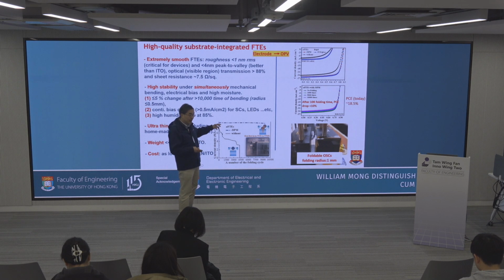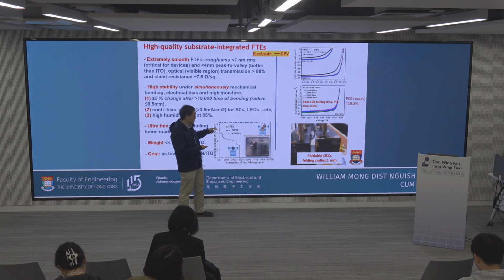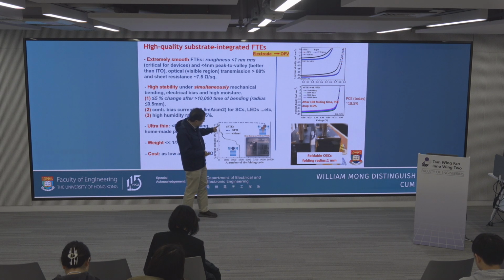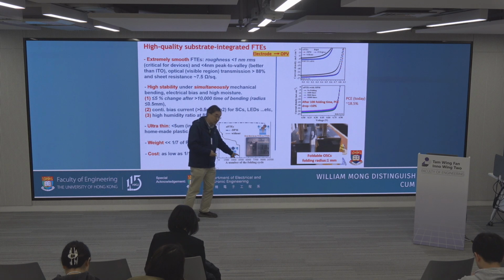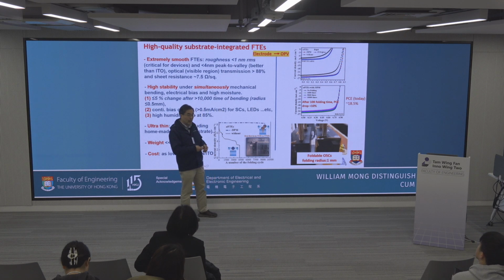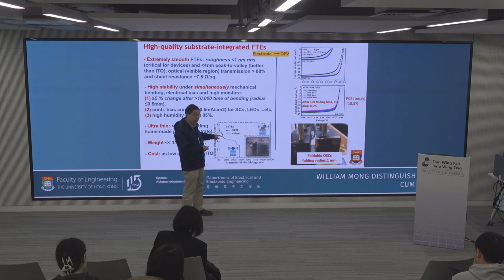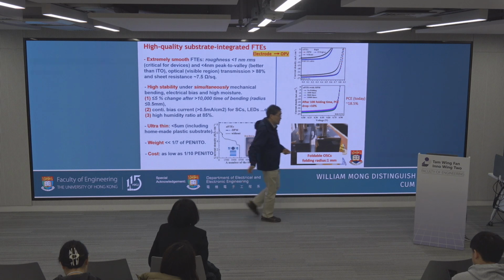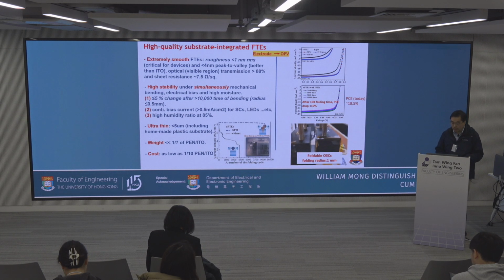The oxide-wire composite produced in the previous slide is potentially useful for devices as a transparent electrode. Compared to the control, where you buy those ingredients, silver wire and oxide, mixed without our process, they will break down quickly. And the breakdown is interesting. You can see randomly they have a big jump. This big jump is because the silver wire heats up during operation, and during bending there is some stress, so they will break. Whenever a silver wire breaks, you have a big drop in conductivity. That's the reason they are not very durable compared to our device in terms of stability.